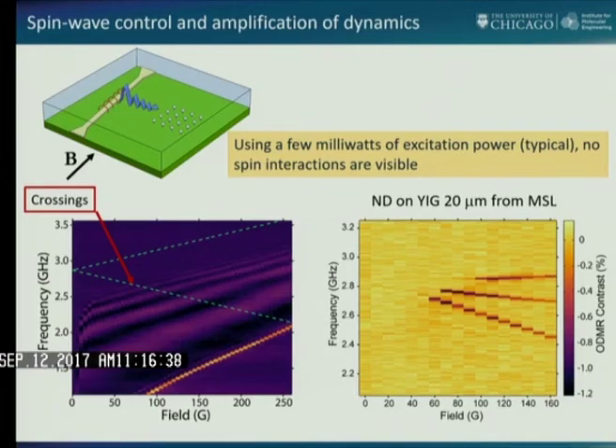gliding through this quantum state. And there are 3 resonances here because these diamonds are pretty poor, and these spins are pointing in 3 different directions. So these are the different spins that are probing in one diamond. But it worked. But we didn't understand why it worked so well. For a long time, we assumed that we were seeing stray fields from the experiment. This was not the spin wave, because how could it work 1,000 times better than it should?